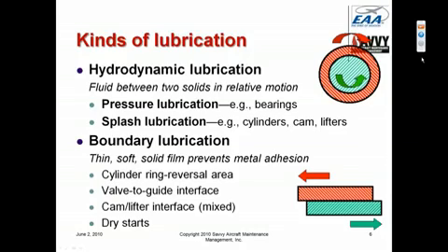The second kind of lubrication, again, is boundary lubrication, which is not a liquid that separates the two surfaces, but a thin, soft, solid film of some sort, typically provided by various additives in the engine oil, that prevents metal adhesion by inhibiting the formation of microwelds. Key areas in the engine that rely mostly on boundary lubrication are, once again, the cylinder in the ring reversal area at top dead center and at bottom dead center, but particularly at top dead center because there's a lot more pressure at that point, to provide some sort of lubrication between the compression rings and the cylinder wall at the point where the piston is slowing to a stop and reversing direction, and hydrodynamic lubrication just stops working.